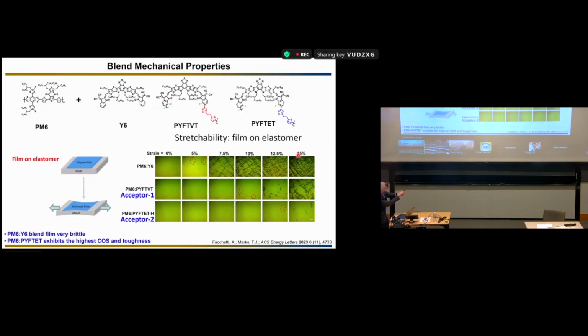So if you take the blend of this donor with the molecular acceptor, this starts cracking at about 5%. If you use the acceptor 1, it starts cracking at about 10% strain. And then if you use the acceptor 2, you are between 12.5% and 15%. So you really start getting blends which are more stretchable.